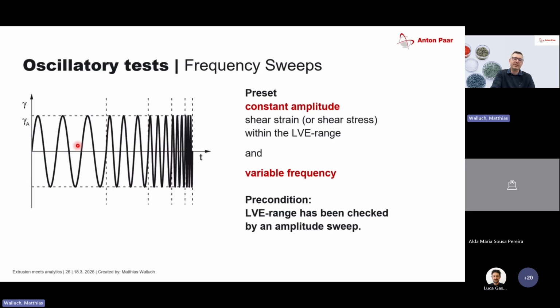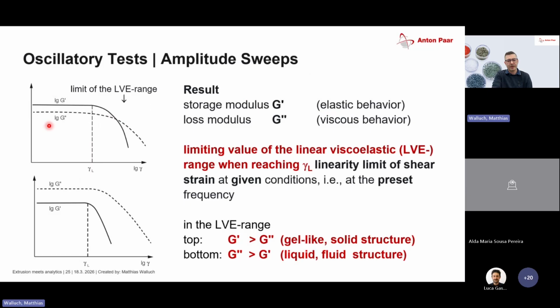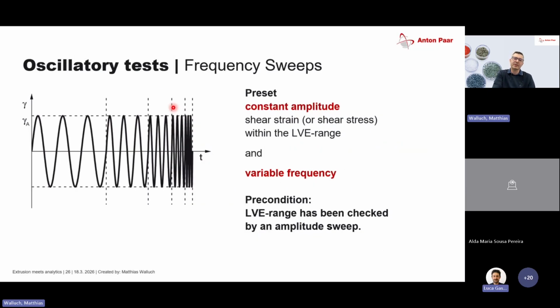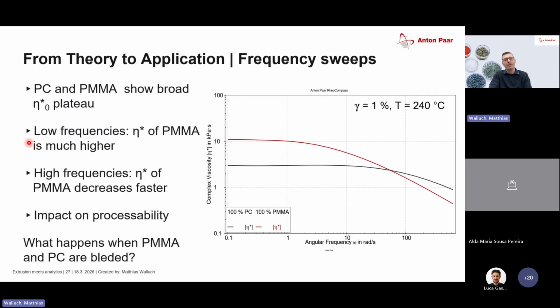Now let's come to the frequency sweeps. So once I know my linear viscoelastic range, which I just found out here, I can do a frequency sweep within the linear viscoelastic range. So this means I apply different frequencies, different speeds, and see how the material reacts. This is comparable to the shear rate, as we will see later on. And with this, we just see the material behavior over time at different speeds, and we get information about the material behavior during processing. Why is this important?